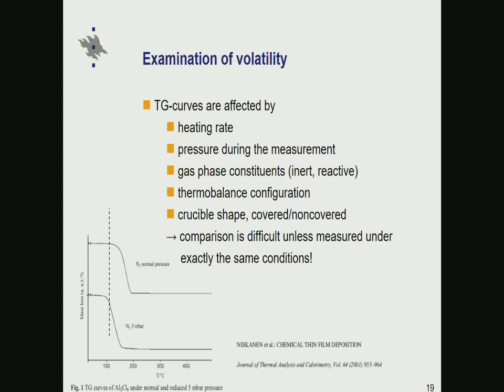Pressure also affects how rapidly the evaporation takes place. So here are two curves. One is measured at normal pressure, and this one is at 5 millibars, which is the ALD reactor operation pressure in our case at least. One can see that under reduced pressure, evaporation starts to take place already at about 110 or so, whereas at normal pressure there is hardly any mass drop yet. So this is simply a consequence of different pressures.